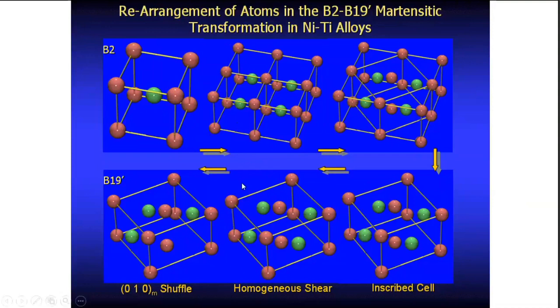But you could have instances where you have only dilatation, or you have only shear, or you have only shuffle. All three, nature plays with this, and everything is possible. But martensite is different from all of them in the sense that it is dominated by a shear. So it's essentially a shear transformation. The dilatation here is less than 1%. And you have a little bit of shuffle.